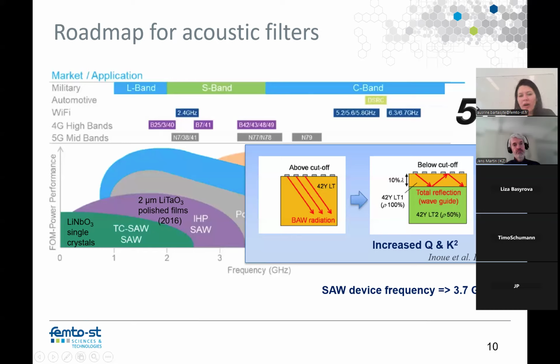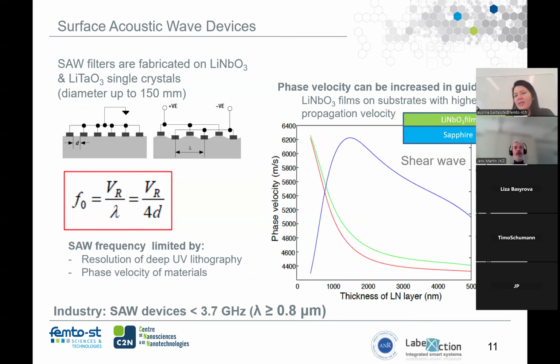So far, surface acoustic wave devices at industrial scale were limited to these frequencies. If you want to go further, the frequency is limited by the interdigital electrode wavelength or period, which is limited by stepper technology. Basically, the wavelength in industrial processes is limited to 0.8 micron. With a single crystal, the velocity is limited by the material velocity, which we cannot change. But we could increase the velocity by putting a film of lithium niobate on a high velocity acoustic substrate, for example sapphire, silicon carbide, which is highly considered now, or diamond. So we need thin layers to increase the velocity.